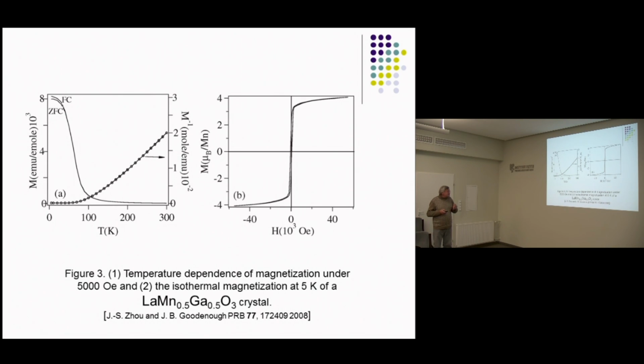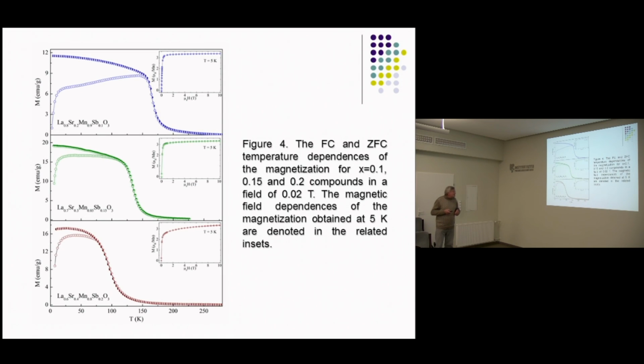The lanthanum manganese O3 doped by gallium also exhibits ferromagnetism, but insulating ferromagnetism, with a Curie point of about 70 degrees. So homovalent compounds exhibit ferromagnetism in spite of the absence of mixed valence. We show that the homovalent antimony or niobium doped compound, homovalent manganese, are also ferromagnets, and exhibit ferromagnetism up to 150 degrees Kelvin.